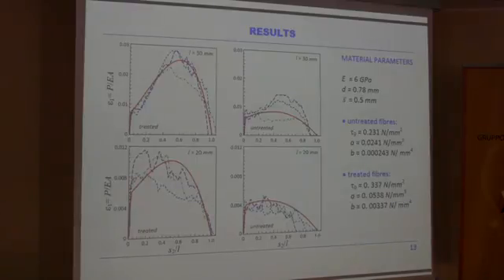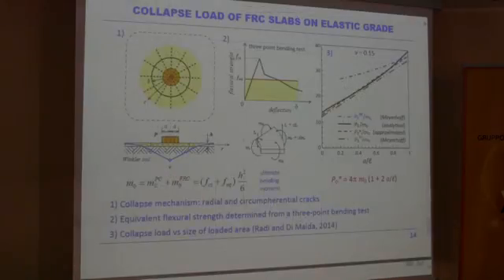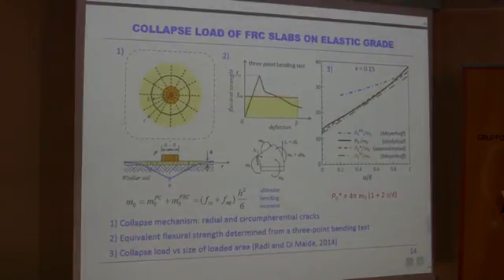So the model has been validated, and the parameters which define the interface constitutive model have been validated by the experimental results. And then we also applied this formulation to study the load carrying capacity of fiber reinforced concrete slabs on elastic grade, and we found an analytical expression of the collapse load, and we compared it with previous approximated or empirical formulas obtained for the definition of the collapse load.